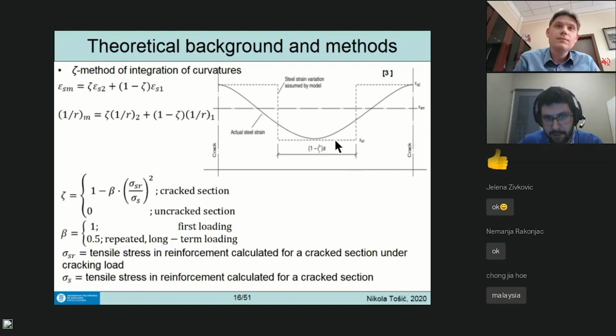So the real behavior, the real development of the strain between the cracks is this. Epsilon S2 would be this value here at the crack, epsilon S1 this value here, that is for the uncracked. But interpolating, we get this block behavior, instead of this.